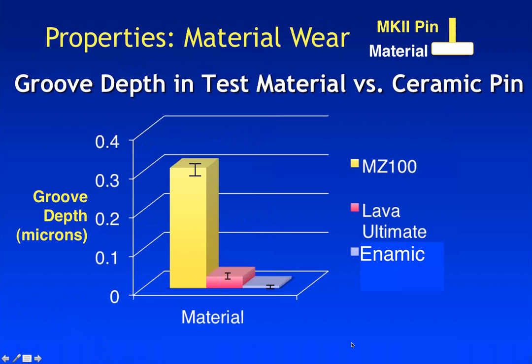We've done our own wear tests. We have wear tests with human enamel, where we make pins out of human enamel, and we run it against the material. In this case, we're making pins out of Mark II because we're waiting for another batch of teeth to come through. It's not easy to get teeth extracted that are acceptable for a wear test. They have to be freshly extracted. So it's not as easy to do. We're waiting for some more human teeth to come around.